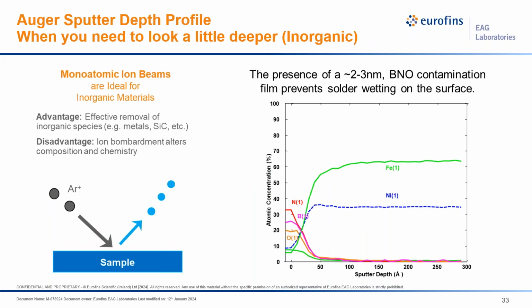So as Alan already mentioned, a little bit of sputter depth profiling. So we can actually introduce an argon ion beam into the process. So we alternate between etching the surface to remove material and then looking at the composition with the Auger beam. And we did that here, and we can see that as a function of sputter depth, the boron, carbon, nitrogen concentrations drop off quickly within the first 2 to 3 nanometers before hitting the Kovar substrate.